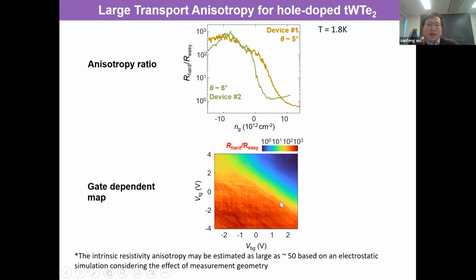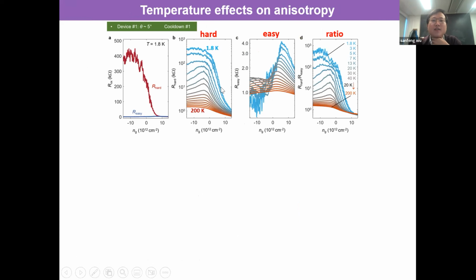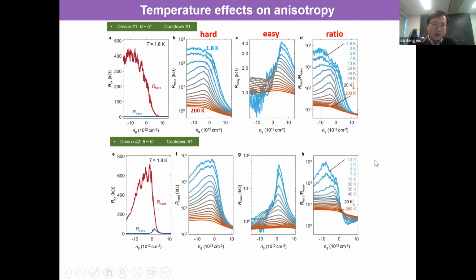The other important aspect is that it's not just the resistance values that are different, they really behave qualitatively different along the 2 directions. What I'm plotting here is one device, measured in the same plot, the resistance as a function of density, measured as a function of temperature. If you look at the hard direction, when you cool down the temperature from 200 Kelvin to 1.8 Kelvin, you see the resistance increase very quickly, right? That looks like a strong insulating state, right? And in the easy direction, however, it's not really changing much, or at very low temperature, you may even see the resistance go down, so like the opposite trend. So it's really qualitatively different along the two directions. Very similar behavior is seen in other devices too.